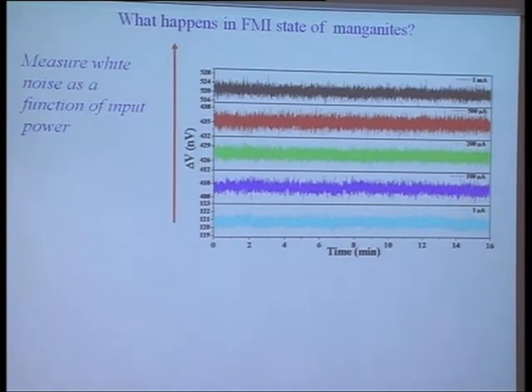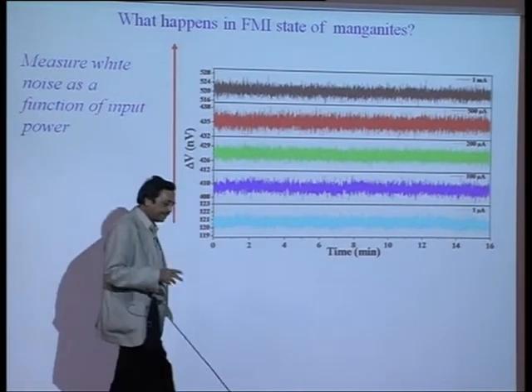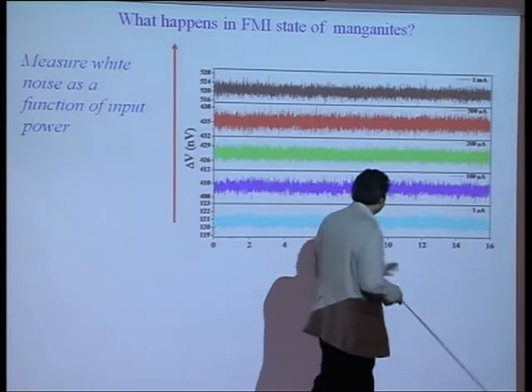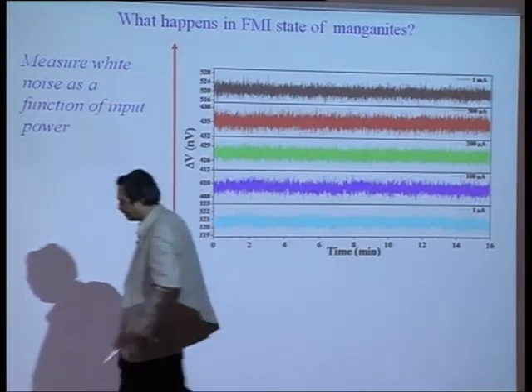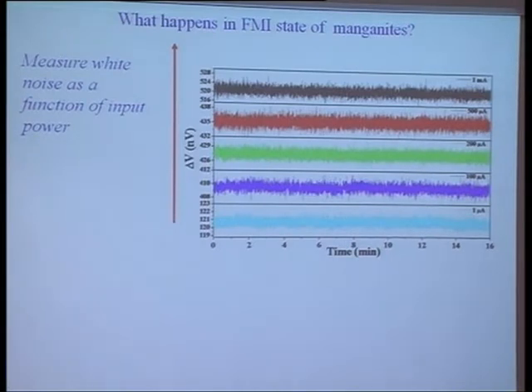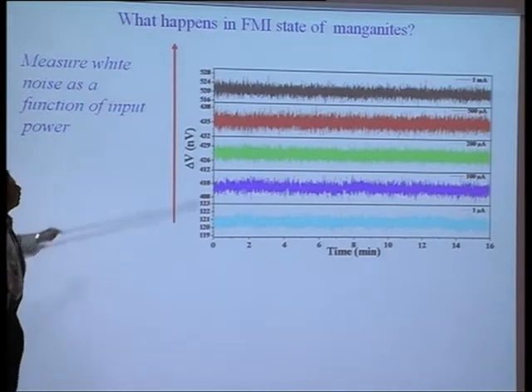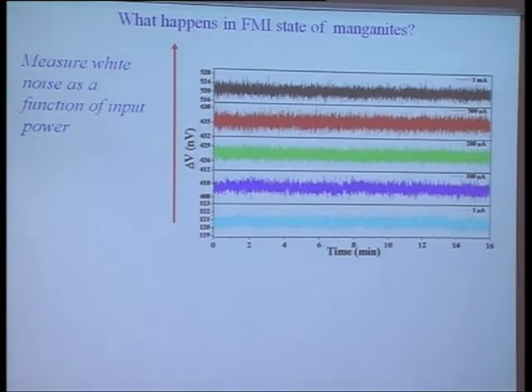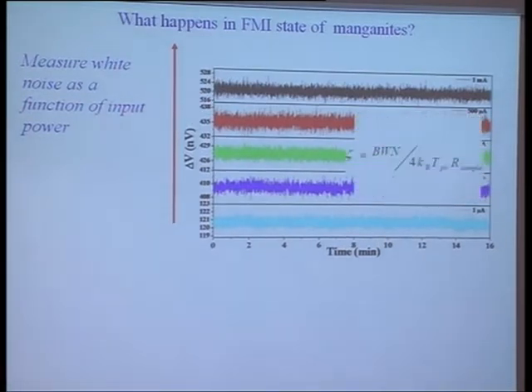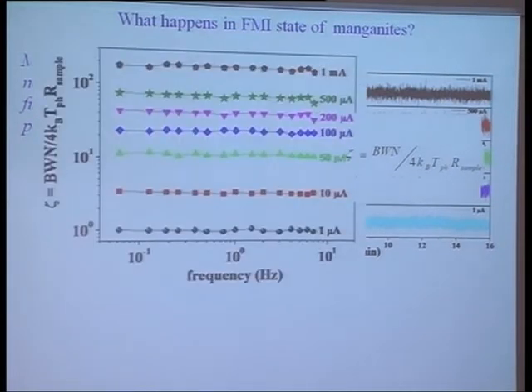This is a very important test that your measurement is correct and the resistor you have purchased is a good resistor. When you come to manganites, when you change the input power, and the way you do the experiment is that we apply a DC and measure the noise in AC. This technique has actually been developed over here, and we are using that. And you can see that as we increase the measuring power, the white noise has started changing. And we again define the quantity, where we measure the background noise and divide it by the Nyquist noise. And we start seeing horrendously large numbers coming up if you go to a very high power.